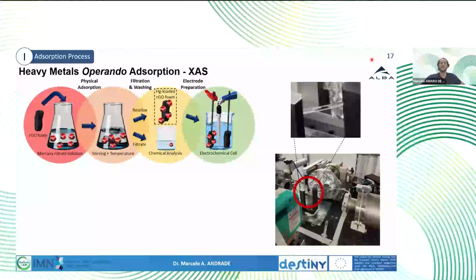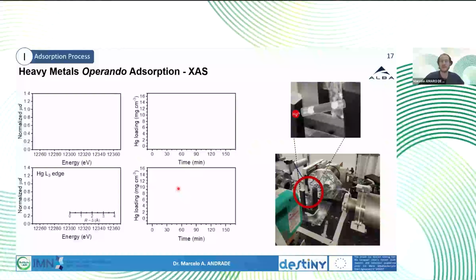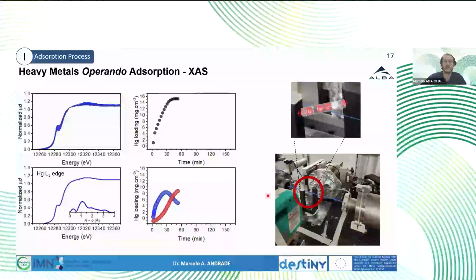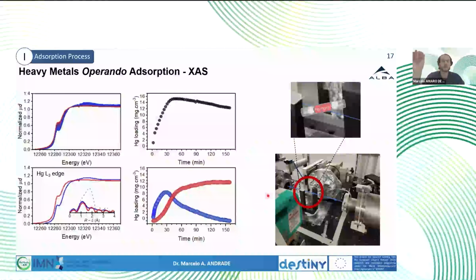So we went to ALBA to perform more or less the same experiment. Here it was not a peristaltic pump, it was a syringe pusher. We had a syringe controlling the amount of solution that was flowing with time. So the idea was the same. We were flowing mercury solution here, and inside this tube we placed the RGO foam that was trapped there with some cotton. We started flowing the mercury solution and also recording the XAS spectra operando. So we could see mercury going through the tube, and we could see the XAS, the L3 mercury edge, changing with time.